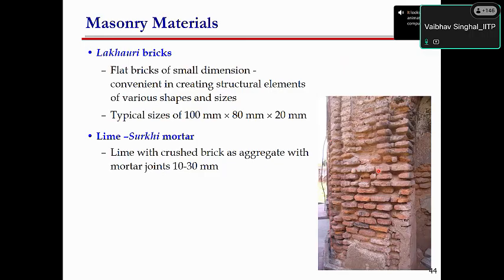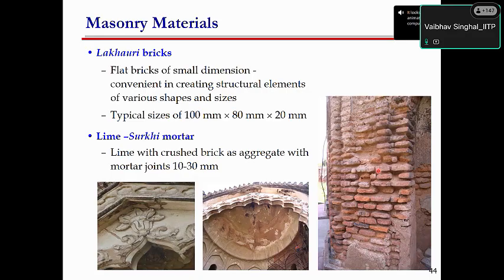So Nalanda will have a typical brick, a thick brick, a bigger brick, but a very thin mortar, thickness not more than 3-4 mm. Whereas in these monuments, especially the monuments of the Mughal era, it is totally different. They have a thin brick but a thicker mortar. So these are some damages which have been seen.